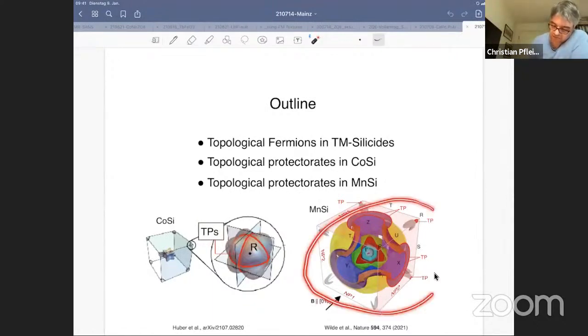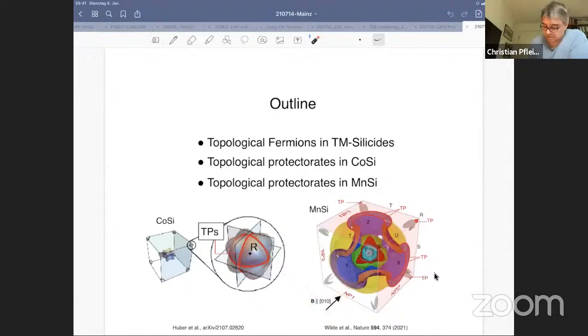So this is the Fermi surface of MnSi. It's much more complicated. And when we apply a magnetic field in a field polarized phase, these nodal planes basically are suppressed in the direction of the field. So on these faces here of the Brillouin zone, they are suppressed. But on the faces perpendicular to the applied field, nodal planes survive, and they enforce, whenever Fermi surfaces are crossing these planes, these topological crossings, right? So these are topological protectorates.